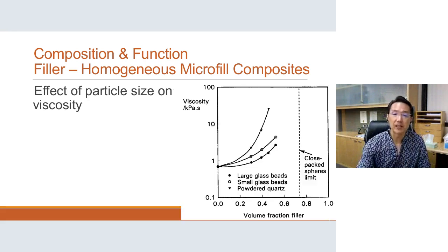viscosity exponentially. So if we look at this graph here, this is volume fraction of filler, and this is viscosity. And please note that this is a log scale, okay? And this is going from the smallest powdered quartz all the way to large glass beads. And you'll see that first, if you increase volume fraction or loading, you get an exponential increase in viscosity. But then if you reduce the size, then it further increases the viscosity exponentially, okay? And in fact, with these microparticles, the microfill, about 2% actually gives you a stiff paste. 2%, and we're talking composites that need to be filled to 70 to 80%. Okay? So this viscosity effect is humongous, and is a major problem in composite design.